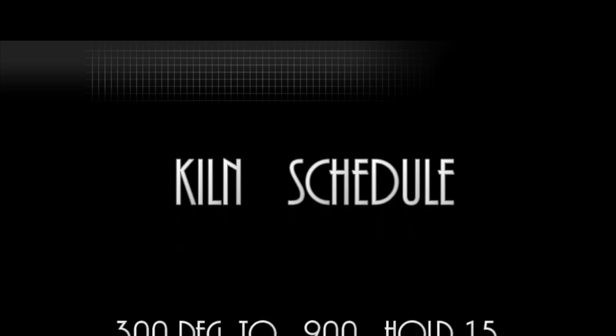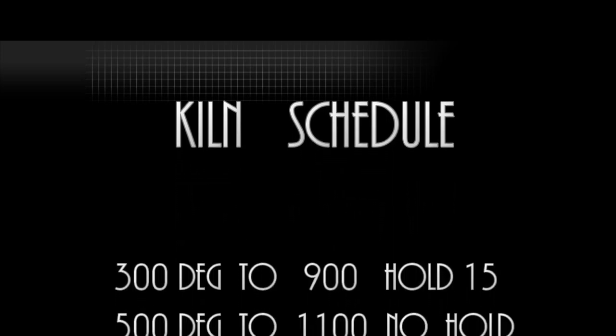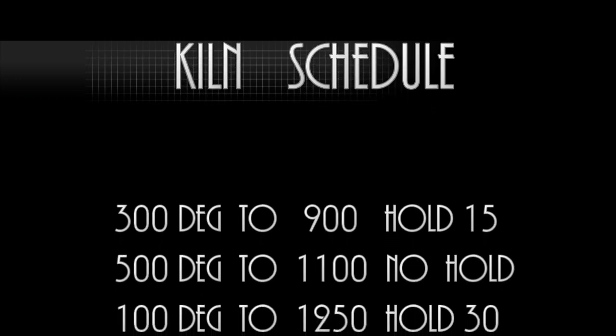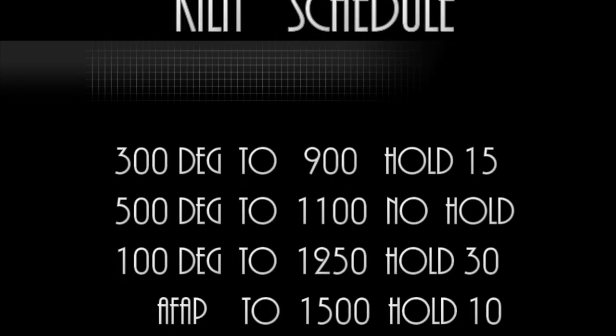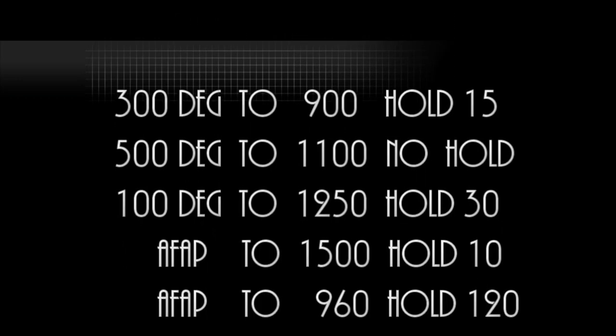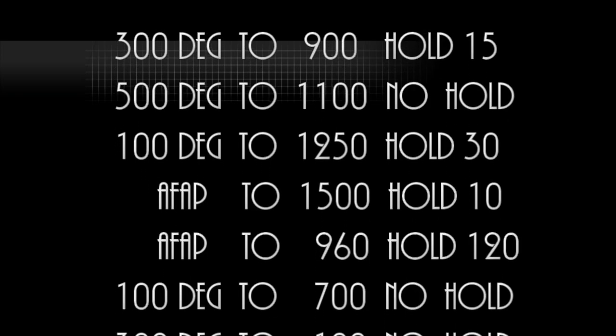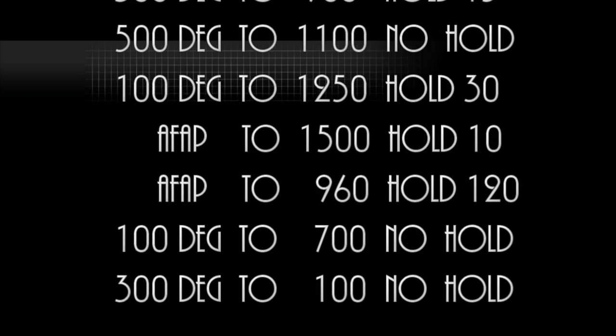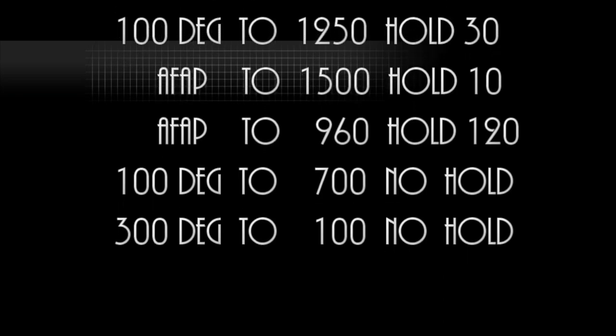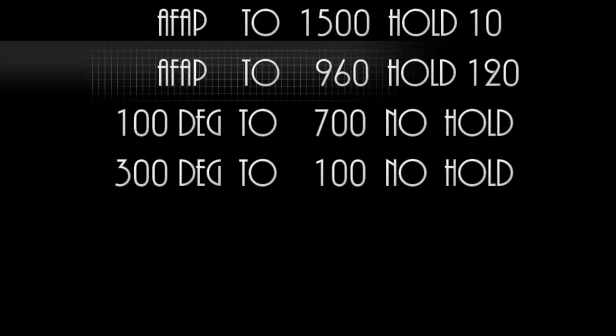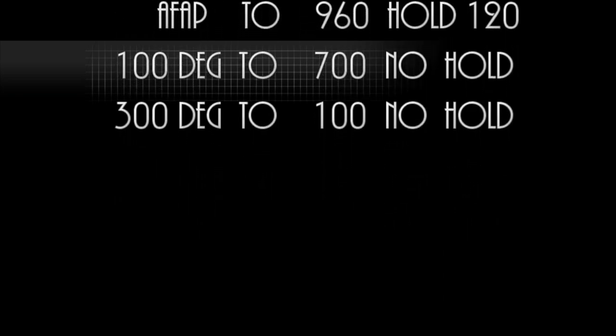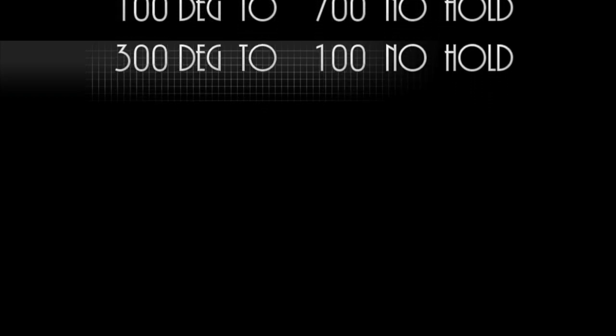The kiln schedule is for a full fuse. You can come back and copy it later, but we go at a rate of 300 degrees to 900 and hold for 15, 500 degrees to 1100 with no hold, 100 degrees to 1250 with a hold for 30, as fast as possible to 1500 we hold 10, as fast as possible to 960 hold 120, 100 degrees to 700 with no hold, and finally 300 degrees to 100 with no hold.